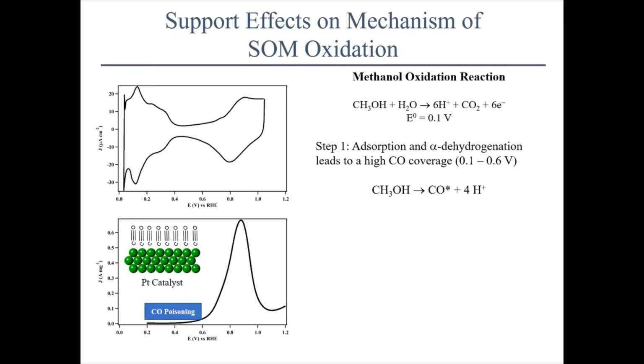And this is really important because the first step is what leads to the biggest problem of methanol oxidation. So at low overpotentials, what you tend to find is that methanol is oxidized to an intermediate, carbon monoxide. And this intermediate carbon monoxide adsorbs to the surface and sticks there, meaning it essentially poisons the catalyst surface at low overpotentials.